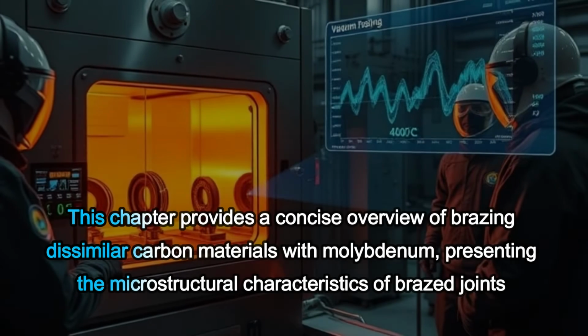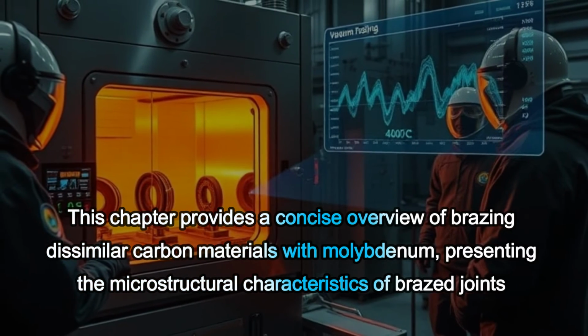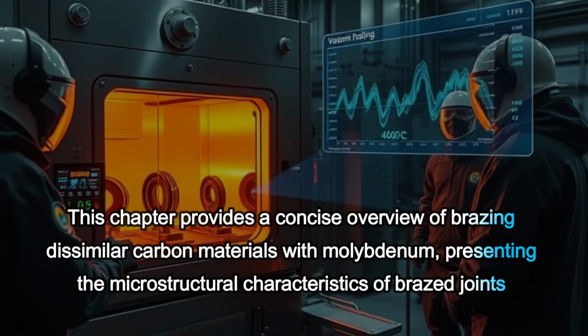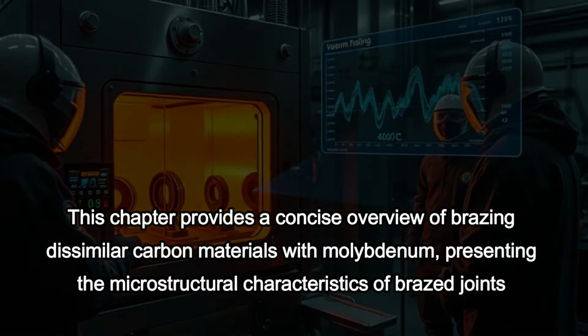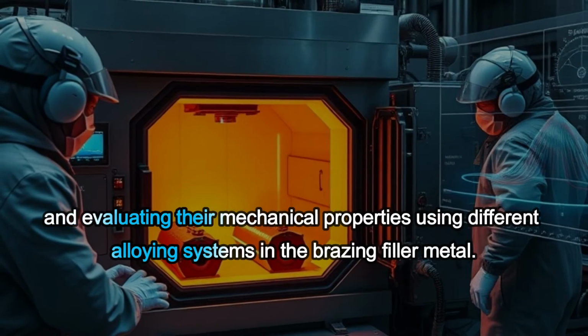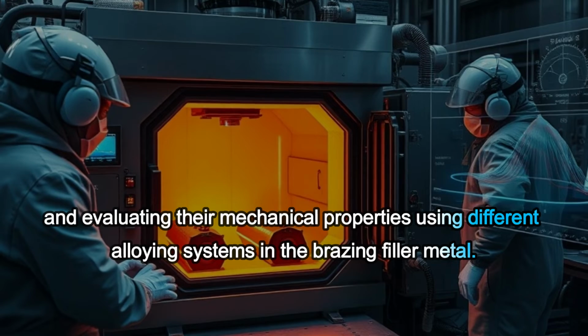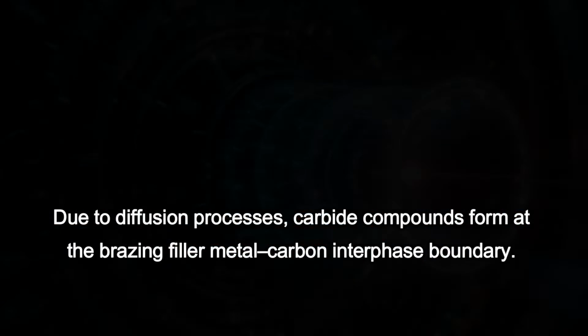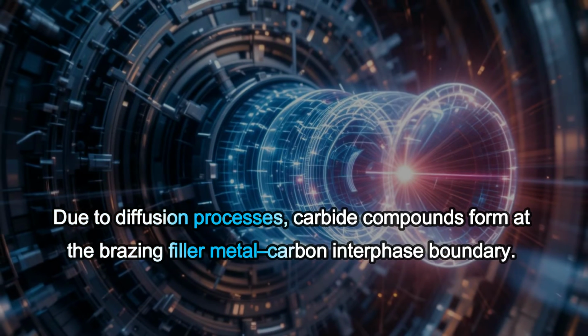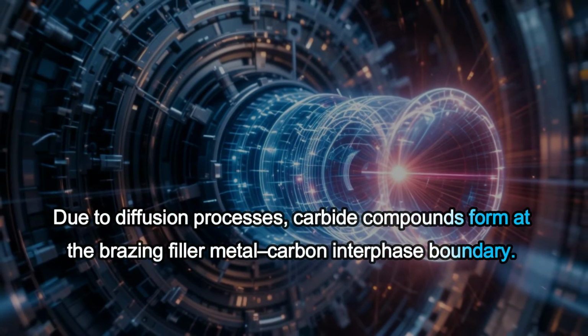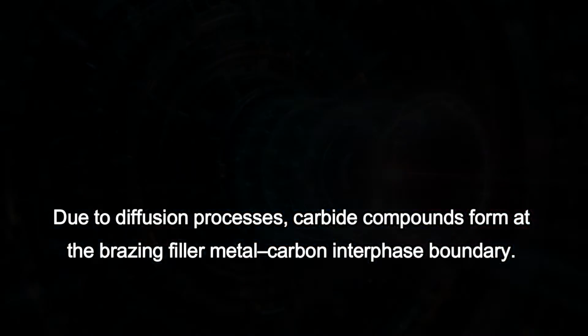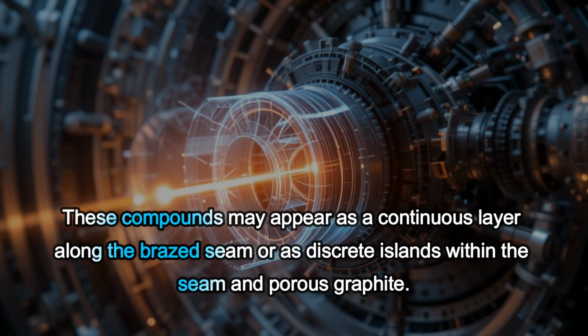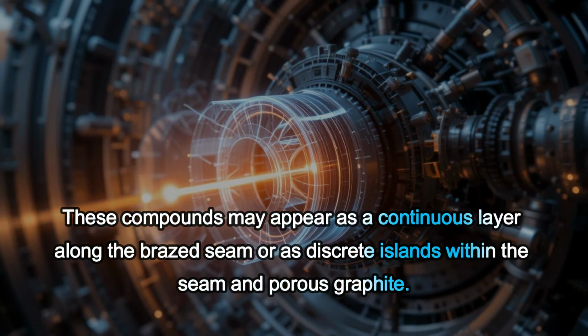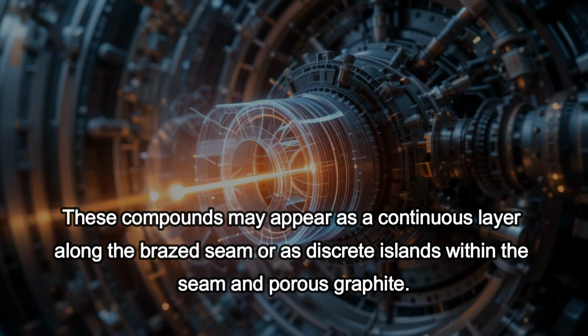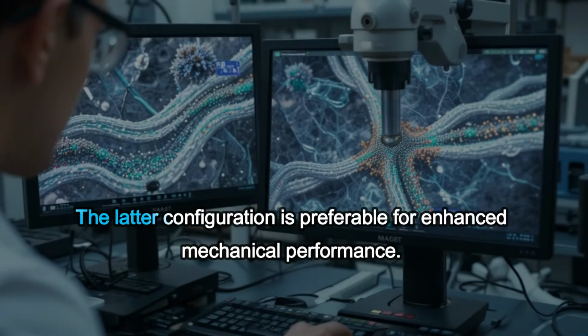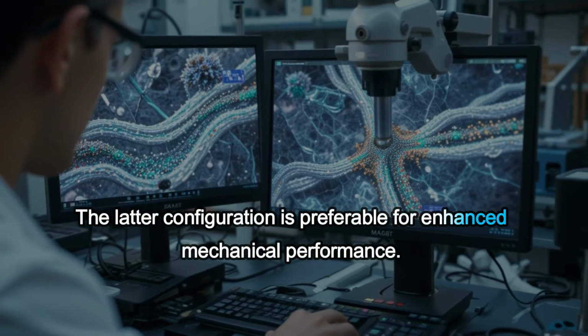This chapter provides a concise overview of brazing dissimilar carbon materials with molybdenum, presenting the microstructural characteristics of brazed joints and evaluating their mechanical properties using different alloying systems in the brazing filler metal. Due to diffusion processes, carbide compounds form at the brazing filler metal carbon interphase boundary. These compounds may appear as a continuous layer along the brazed seam or as discrete islands within the seam and porous graphite. The latter configuration is preferable for enhanced mechanical performance.